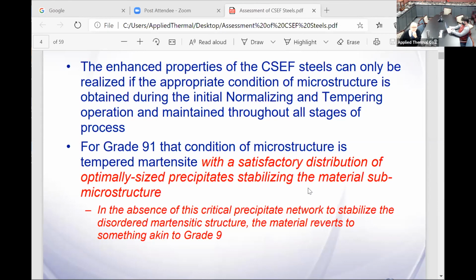Obviously, you learned about the microstructure being tempered martensite. In the absence of the critical precipitate network to stabilize the disordered martensite structure, the material reverts to something akin to grade 9. So what this is saying is, if the proper procedures aren't used, you might as well skip 91 and just use grade 9.